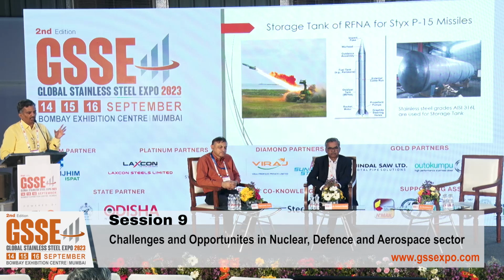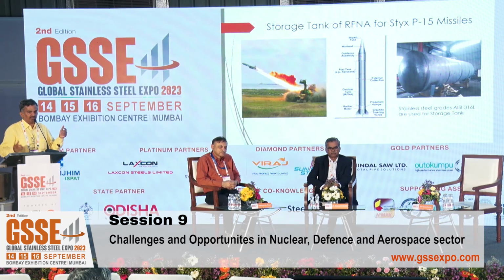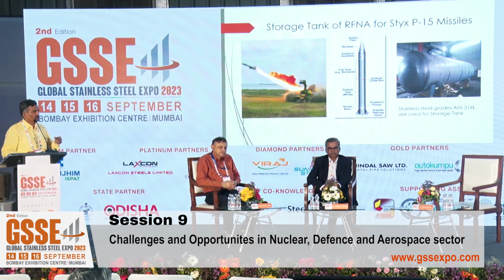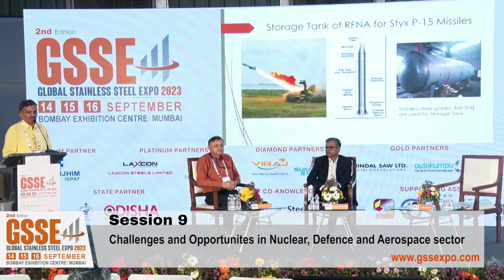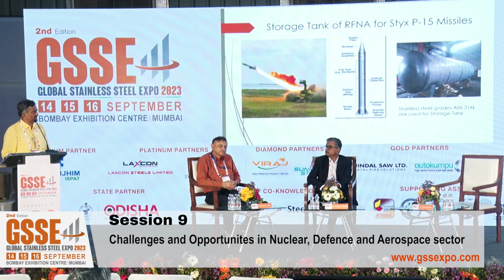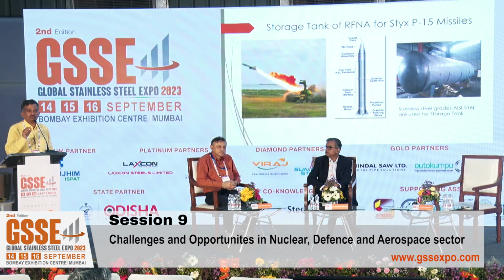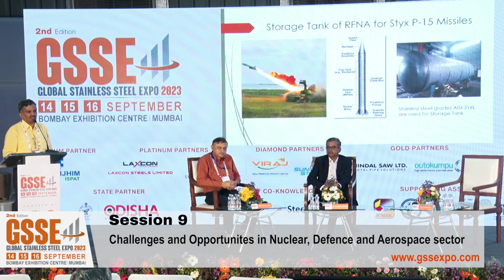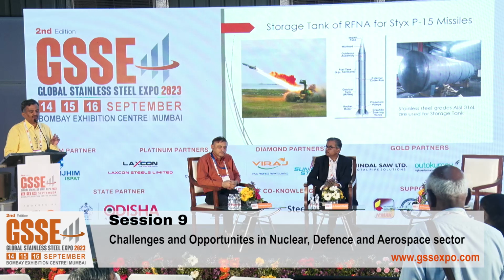Basically, red fuming nitric acid, when mixed and fired, it produces very heavy missiles. Here, the fuming nitric acid tanks are basically stainless steel 316 based, and the valves inside are high chromium based. The chromium count is around 25 to 30%. So that kind of valves are also used.